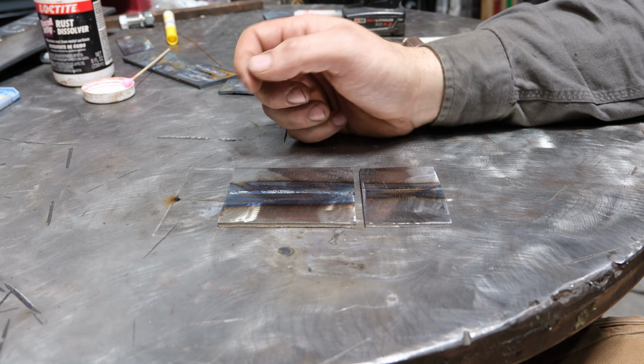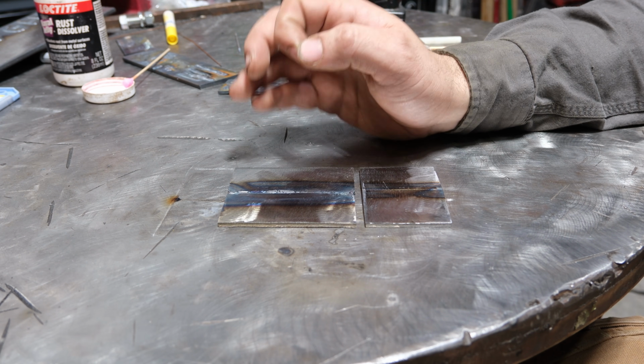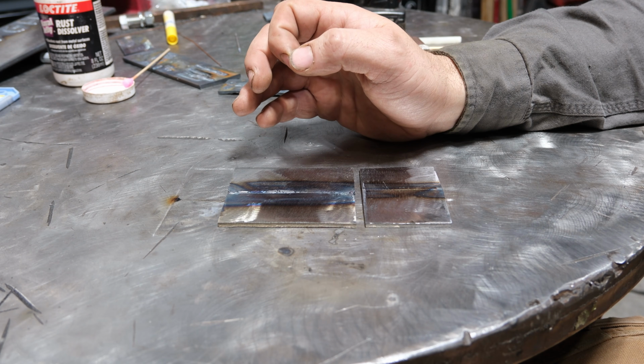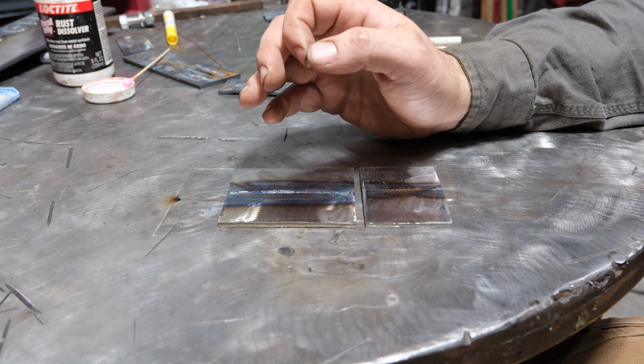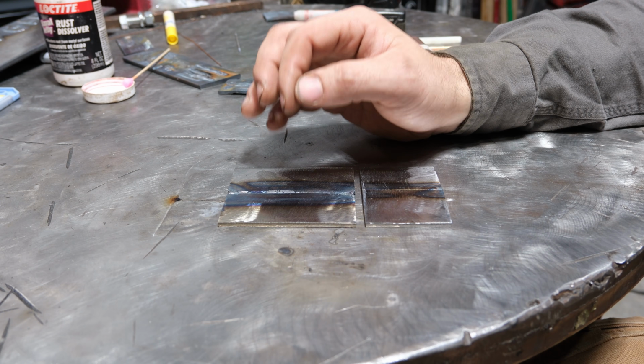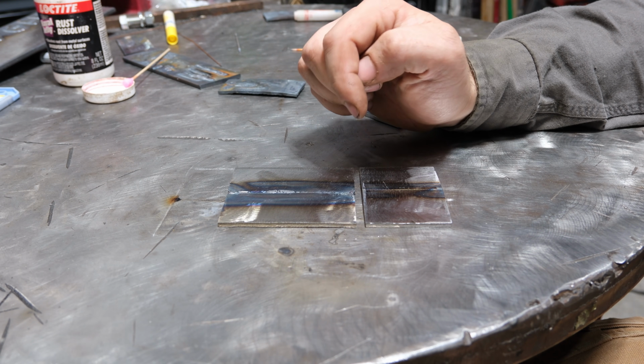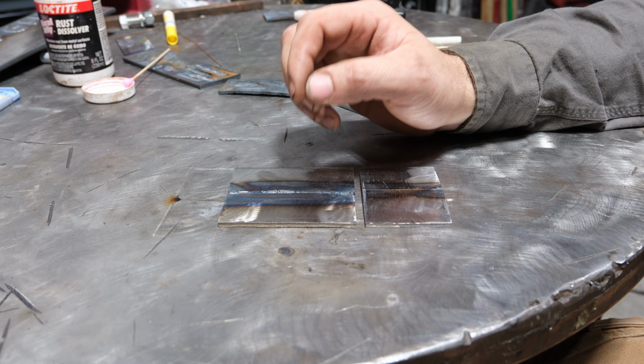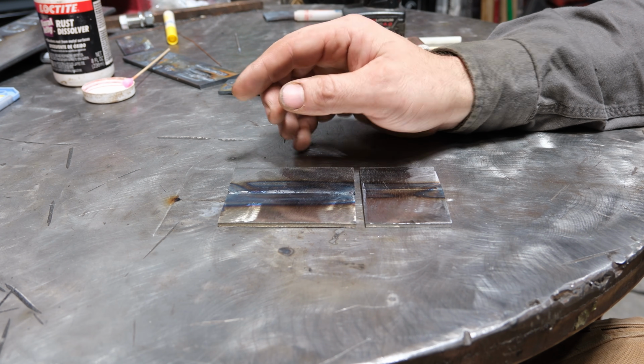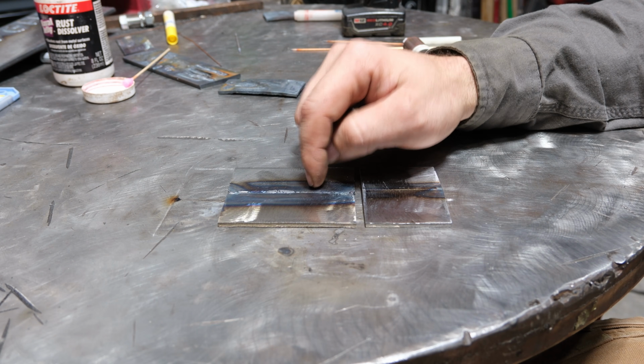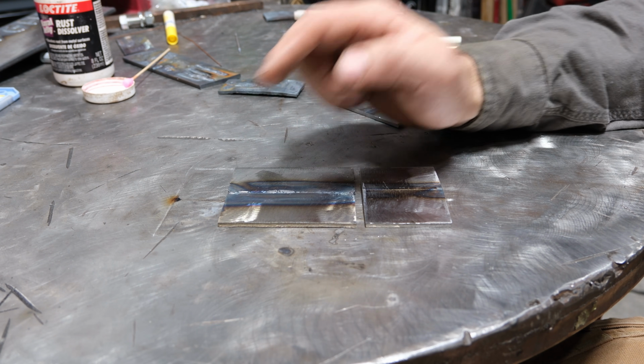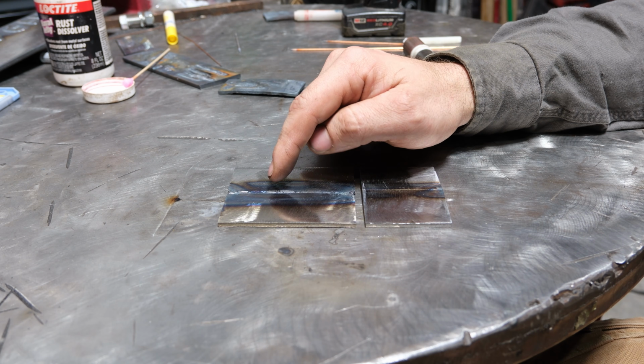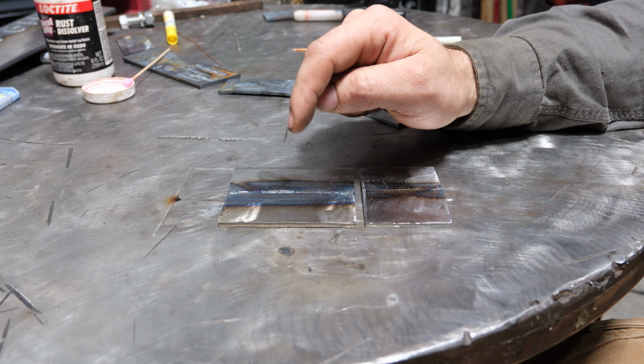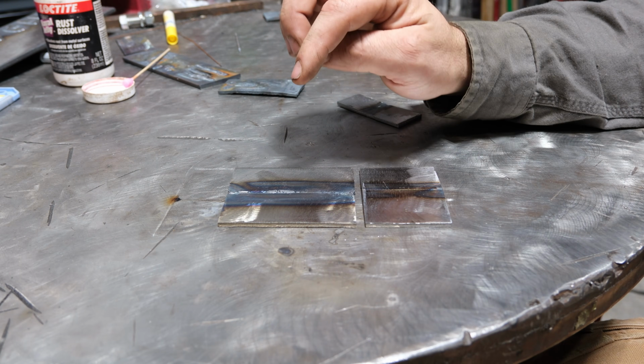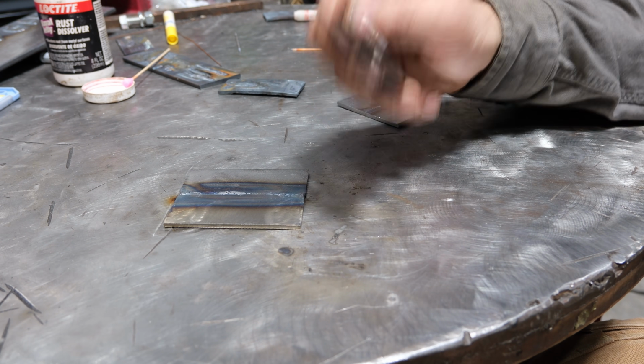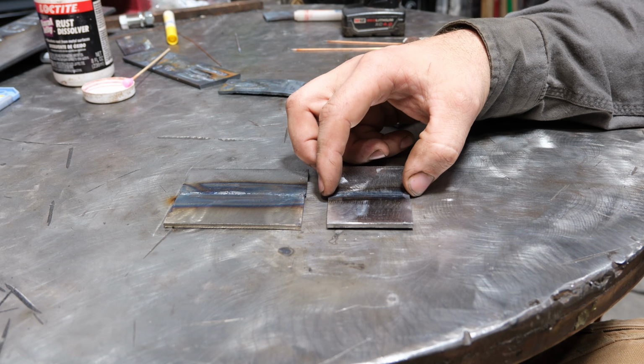And there's a very good reason for that. TIG achieves fusion via amperage and travel speed. It's very common to simply weld too fast, especially with fusion welds, and the end result is a severe lack of fusion, or basically penetration and fusion. By slowing down, which I had to do via adding filler, I was able to actually achieve more fusion and a better result. Now, you can do the same thing with a fusion weld if you simply slow down.